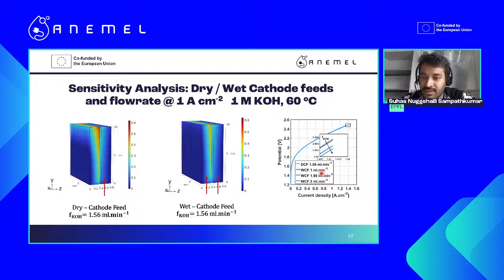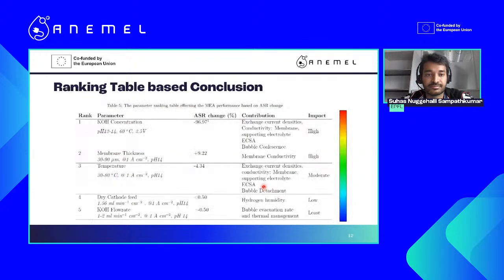Further, we changed the flow rate between 1 to 2 ml per minute in the wet cathode configuration. We also saw quite minimal effect in performance. So larger flow rates do have an improvement in performance, but if you are not in the mass transfer region, this barely has any effect, provided the membrane has sufficient water available to split.